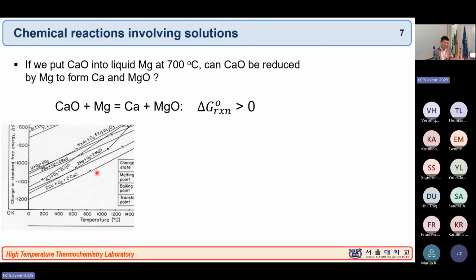So here you can see the calcium oxide in the very bottom, and then you have magnesium oxide just above. If you look at this chemical reaction, CaO plus magnesium becomes Ca plus magnesium oxide, this delta G naught of reaction is always positive. So can this chemical reaction happen or not? Not happen. Come on, not happen. Happen. I don't know.